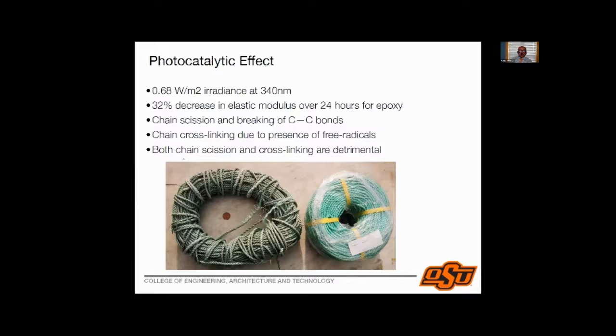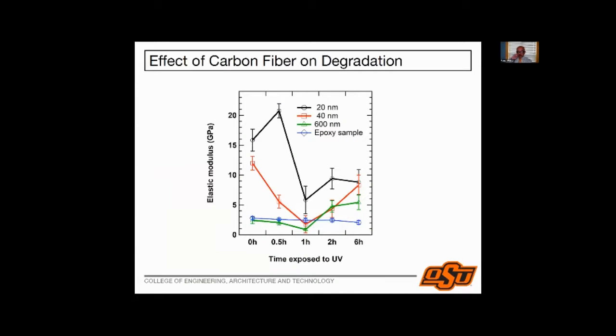So I can pick a certain point and look at the elastic modulus. This is the same data that we are looking at, but looking at it slightly differently. I'm looking at the elastic modulus as a function of duration at various locations on the sample. This is the variation of the elastic modulus at 20 nanometers as I expose that point to UV radiation. The blue line is what I would get if I just took pure epoxy. The green line is the behavior of the polymer at 600 nanometers, and the red and the black lines are closer to the interface region.